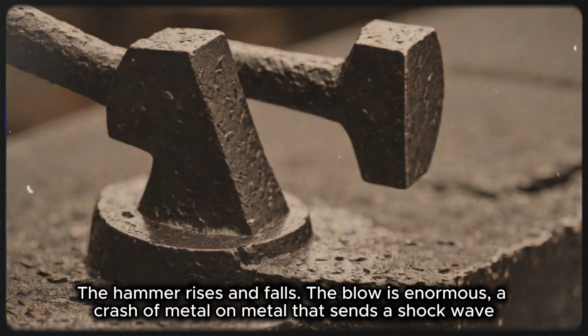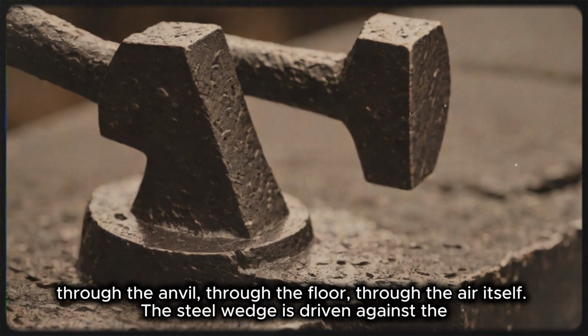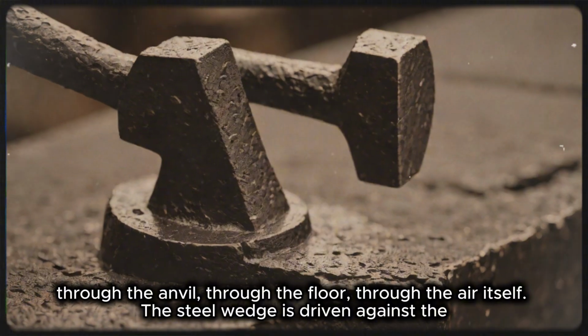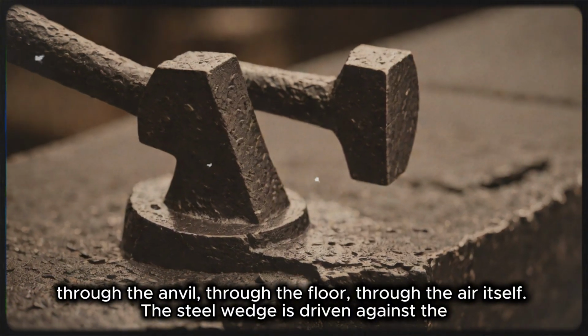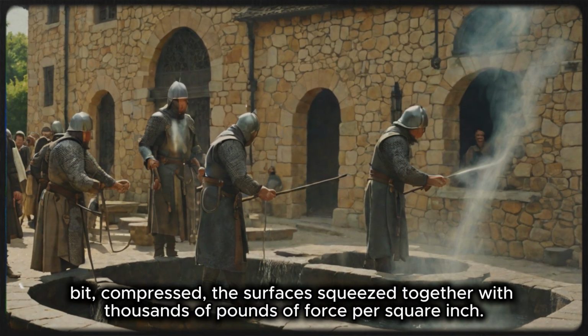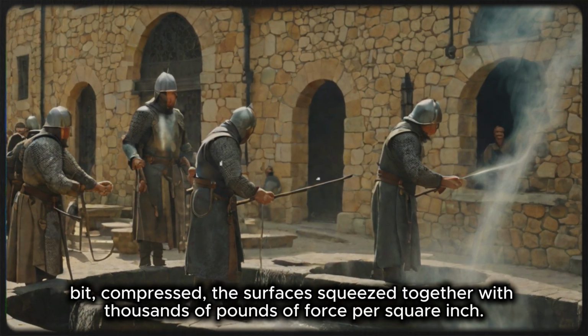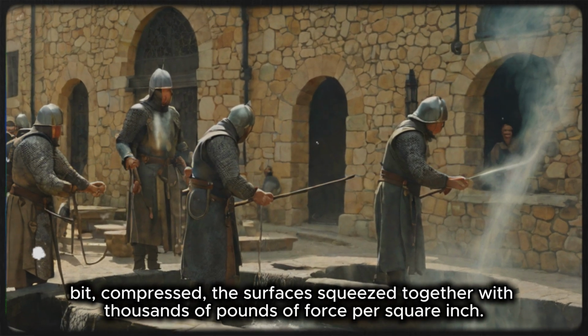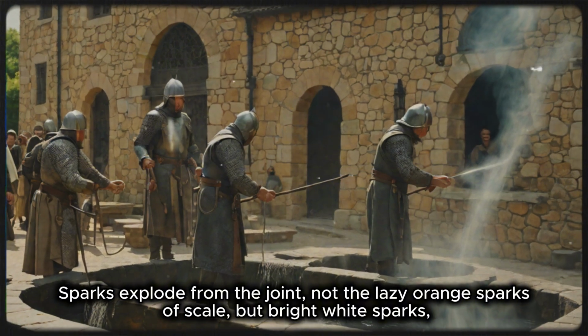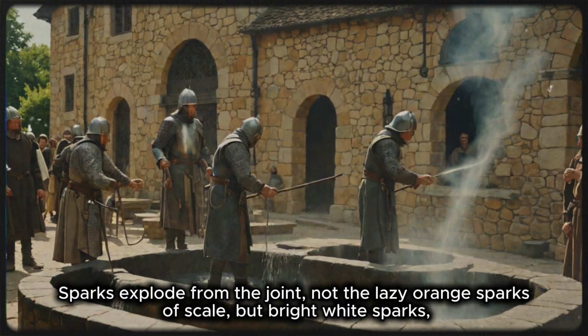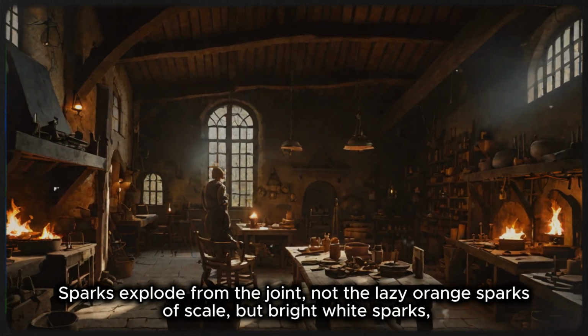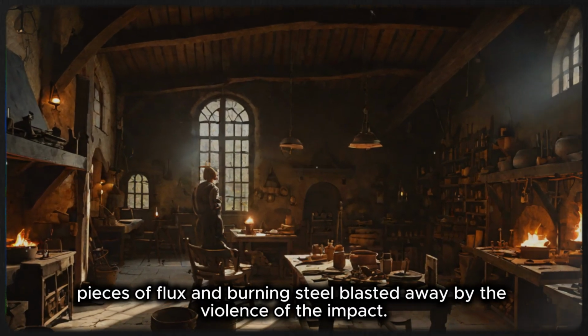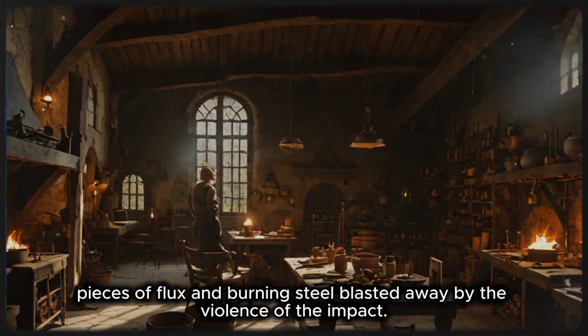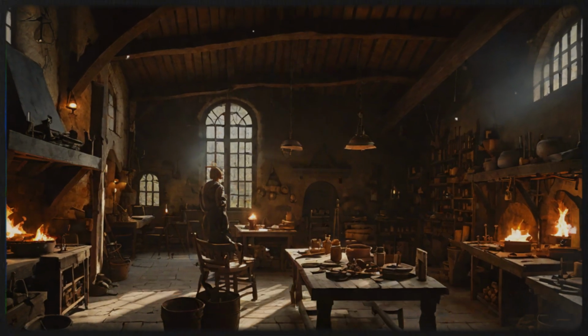a crash of metal on metal that sends a shockwave through the anvil, through the floor, through the air itself. The steel wedge is driven against the bit, compressed, the surfaces squeezed together with thousands of pounds of force per square inch. Sparks explode from the joint, not the lazy orange sparks of scale, but bright white sparks, pieces of flux and burning steel blasted away by the violence of the impact.